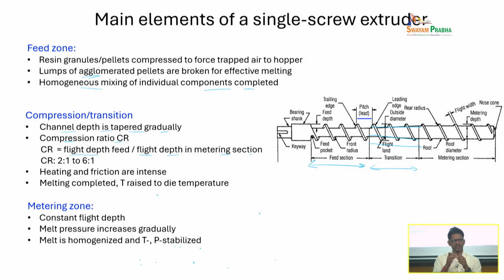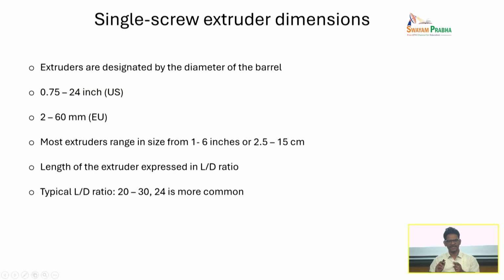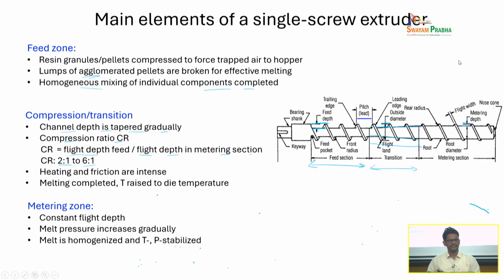So this basically tells you to what extent you are restricting the space to flow in the metering section versus the feed section. This compression ratio can go anywhere between 2:1 to 6:1. So 2:1 means the gap here, you see this gap between the barrel and the surface of the screw, is the depth in the feed location, and this is the location at the transition, and here is the location at the metering section. So from the feed to the metering depth, that ratio we call the compression ratio. The compression ratio can be 2:1 to 6:1.